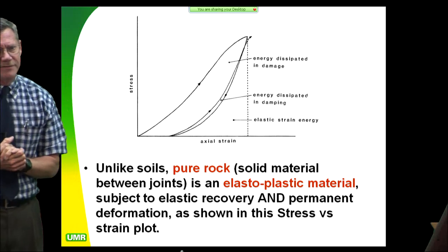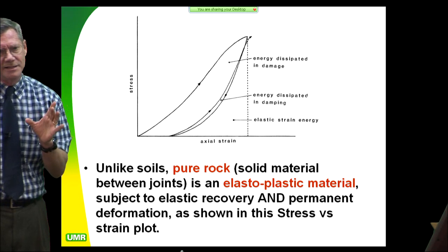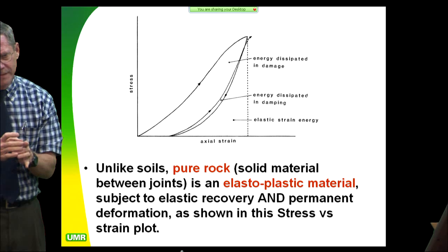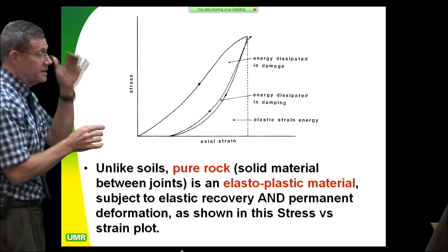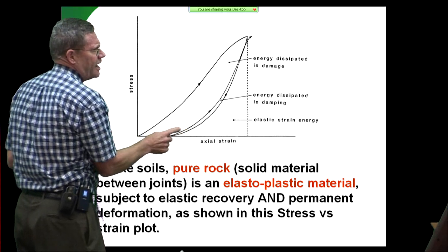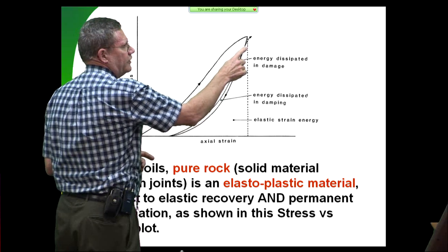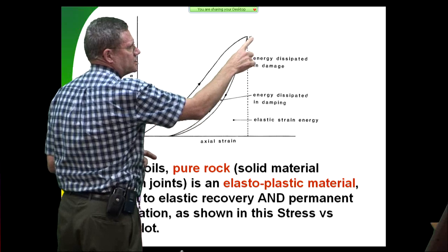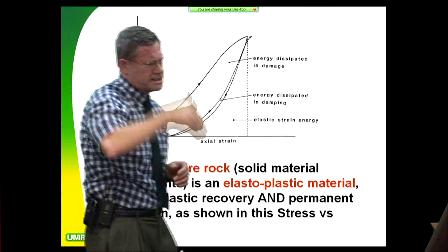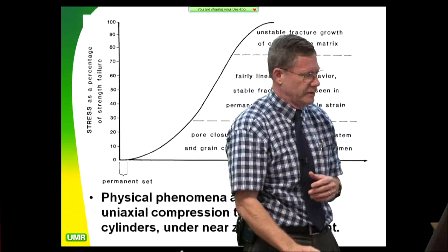You get in a lot of trouble with this if you get a solid mechanics person in there that doesn't understand that rock has all kinds of imperfections in it, and it's highly anisotropic, and it's subject to permanent deformation. So as you go back up this, now you're seeing the true elastic behavior as you reload. Now you get up into here, and it's going to start micro-fissuring again and start breaking and turning over. So it's only by doing this load cycling that you see the true elastoplastic behavior of the rock.